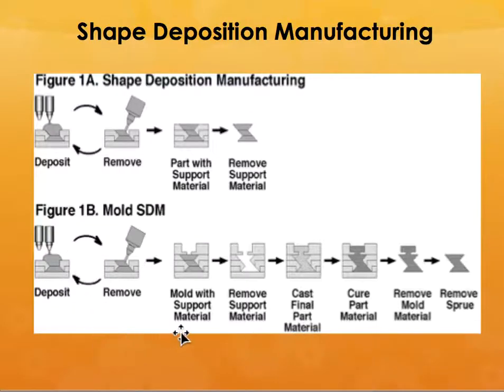The other way would be to deposit this material, which is water soluble and UV curable, and then deposit additional wax on top of that, and then just wash away the inside mold material, so you have a very accurate mold. As I told you, the problem with many of these techniques is that because they are built in layers, you have what are called stair step features. So the edges are not uniform like you would get in the case of a machined sample.